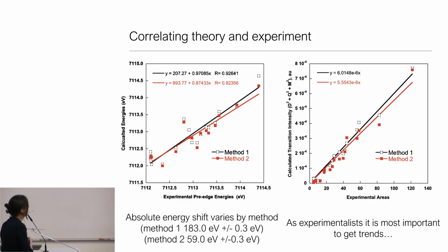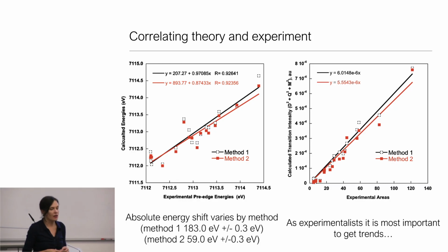And so what we see, these are old numbers now, where we were within about plus or minus 0.3 eV. From some of the ORCA team developments, this is getting closer to plus or minus 0.1 eV. And with areas, we've generally been quite good in terms of the correlations. One thing, though, I'm not telling you about is that I'm focusing on the plus or minus. And what we care about is getting the trends right. So we have to establish scaling factors. At a given level of theory, I need to shift by, in one method, by 183 eV. If I add relativistics, the shifts become smaller. But my point is, I only care what the plus minus is. I don't care what the absolute energy is.